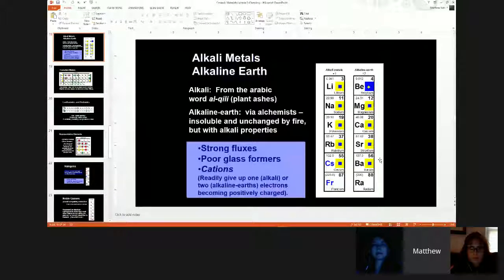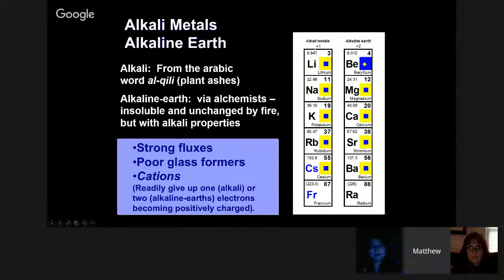Okay, so because that first column of the periodic table, right? Lithium, sodium, potassium, rubidium, cesium, francium. Because they all have that +1 valence, because they all need an electron to bond, they can be substituted for each other in the glaze. And this becomes really, really important as we go forward. The same thing with the second column, magnesium, calcium, strontium, barium, and then zinc comes up as well, that because they have the same atomic structure, we can use them interchangeably, and they still do basically the same thing. And it becomes a really, really neat trick that we can do.